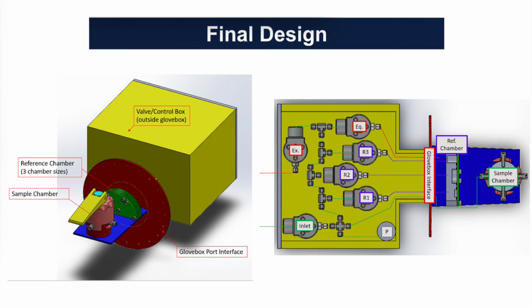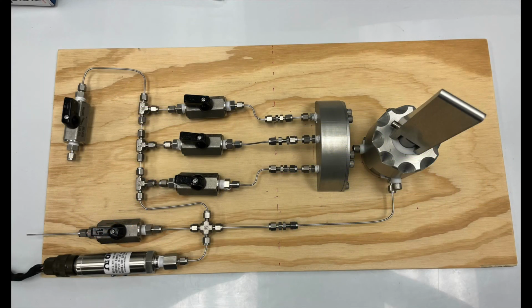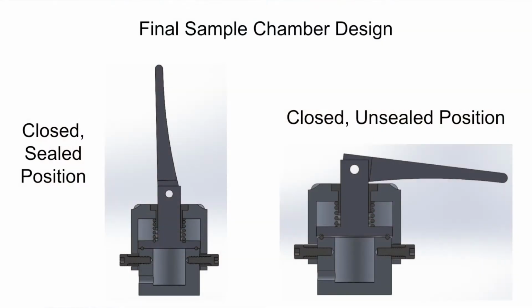The sample and reference chambers will be mounted onto a stand that will protrude into the glove box environment with pass-throughs for tubing. The controls and pressure sensing will be housed in a sealed box that will be affixed to the outside of the glove box via the glove box interface plate. Each reference chamber can be toggled on or off. This design allows for a number of configurations of the reference chamber volumes in order to achieve the best possible results. The final sample chamber design was a slightly modified version of the second iteration.